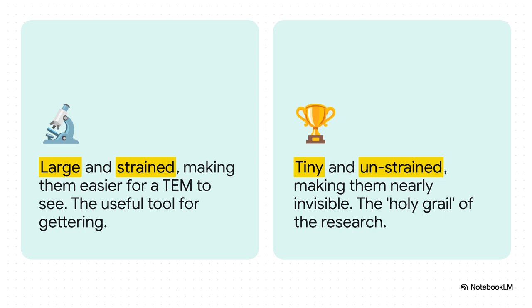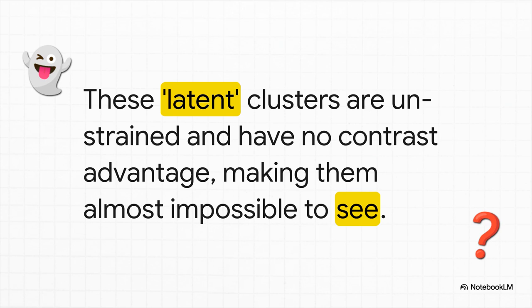But the real prize, what everyone is hunting for, are these so-called latent clusters. They're the exact opposite. Tiny, unstrained, and basically invisible. And that's the core of the problem. These latent clusters, the all-important seeds, are so small and fit so perfectly into the silicon crystal that they don't create any strain. There's no contrast for the electron microscope to pick up. They're like perfect little ghosts, hiding in plain sight. Figuring out a way to find and study these invisible seeds, well, that's the next great frontier in making our technology even closer to perfect.